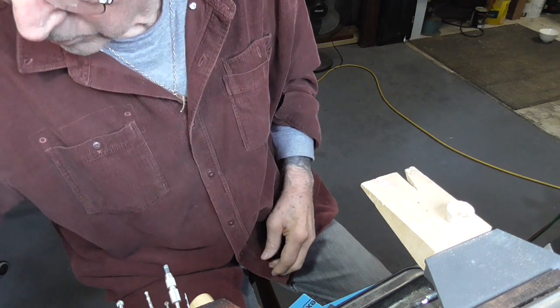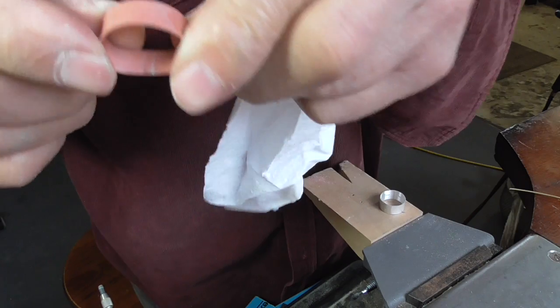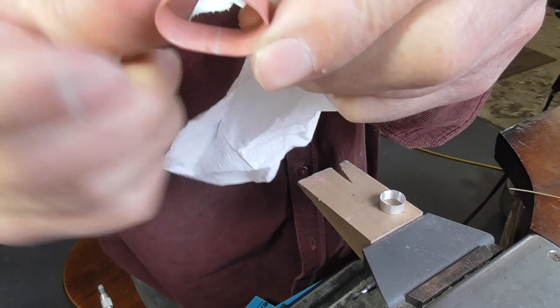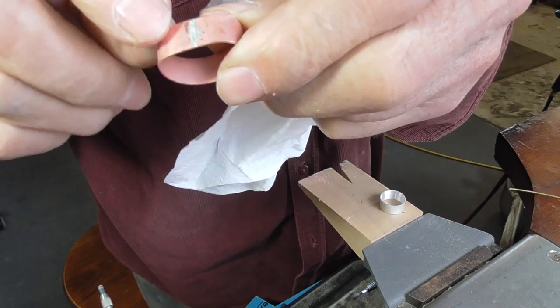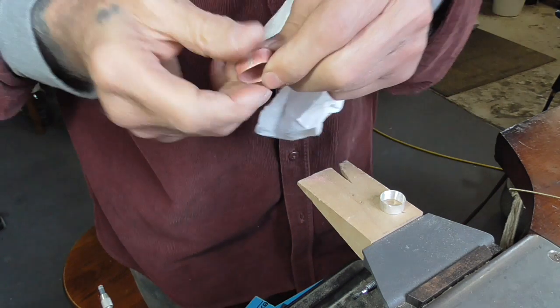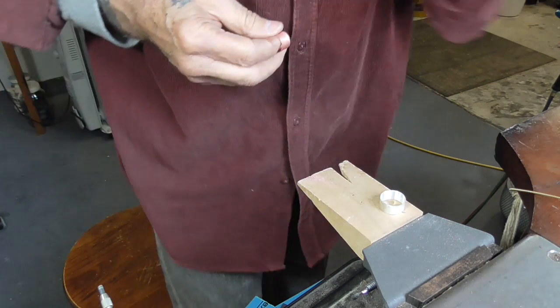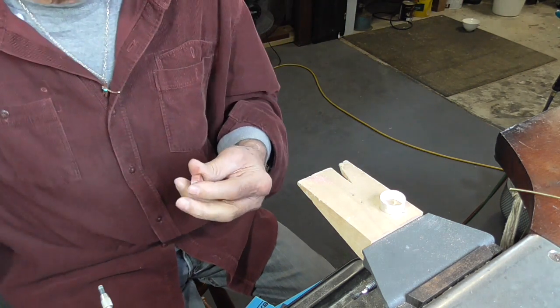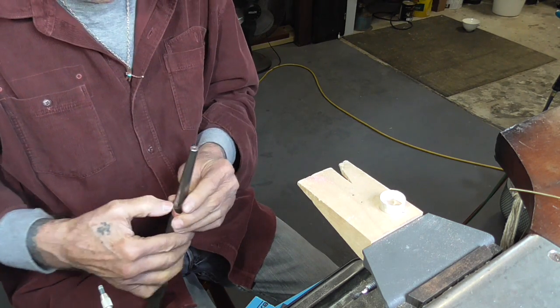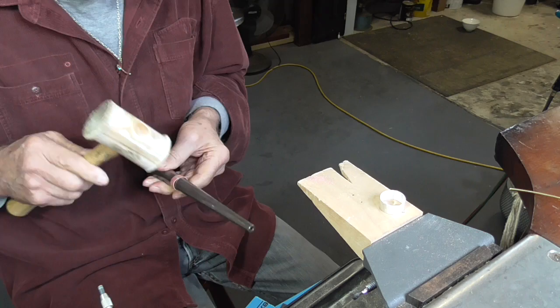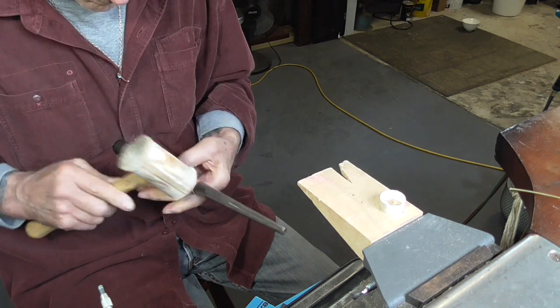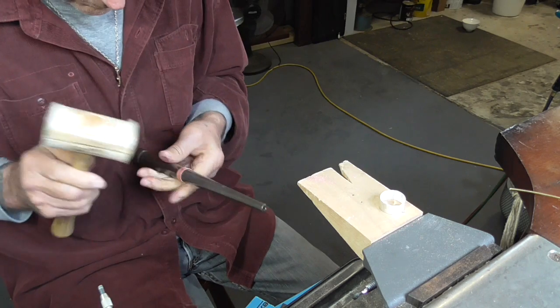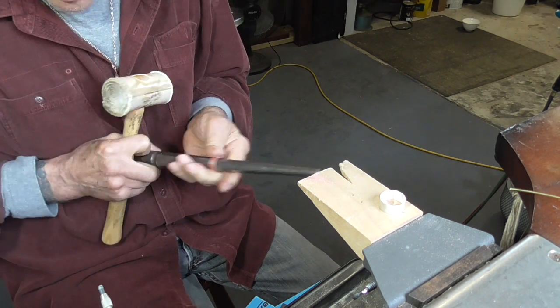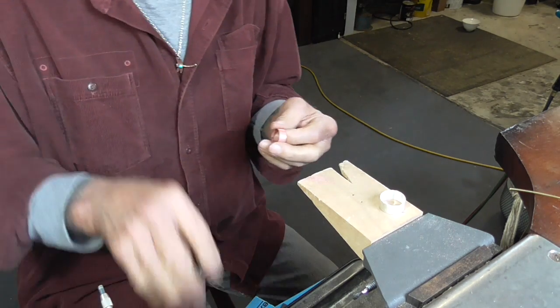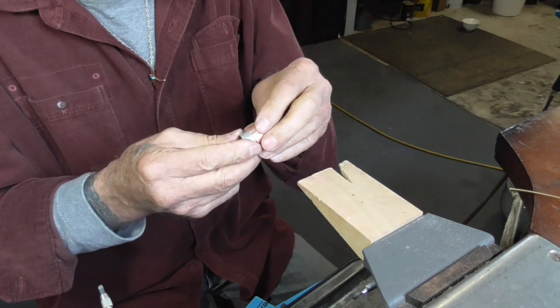So our copper should be ready to take out and tidy up. So dry off the metal, and you can see I have just a fine solder line on the inside to tidy up, and the majority of the solder is out here, and it's always easier to tidy up the stuff on the outside. So we'll just round it up on the ring mandrel with the rawhide hammer. Usually you can just push the ring all the way down. I'm going to check the fit before I do anything else.